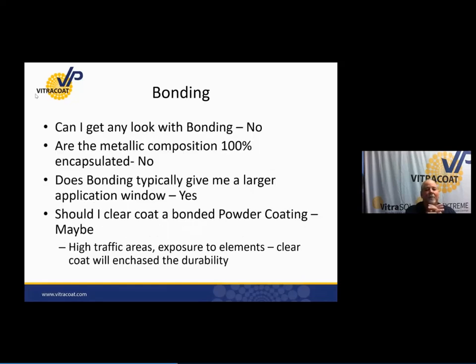And so when you think about the bonding concept, can I get any look with a bond? No, I can't, because of the limitation that it gives me in terms of heating and how it's blended. Sometimes a dry blend will give me a more metallic look. Are there metal compositions with 100% encapsulation? Through bonding, you do not get 100% encapsulation, so no. Does bonding give me a larger application window? Absolutely it will, because you're taking the metallic and you're blending it or bonding it with the other components within that product.